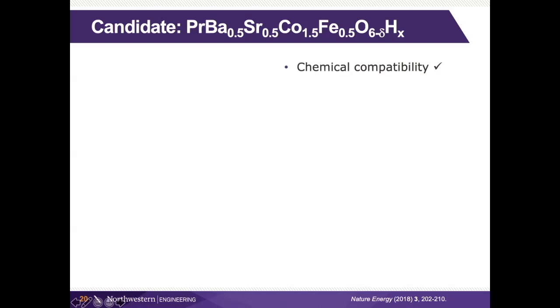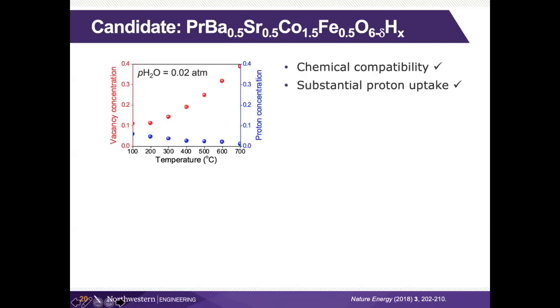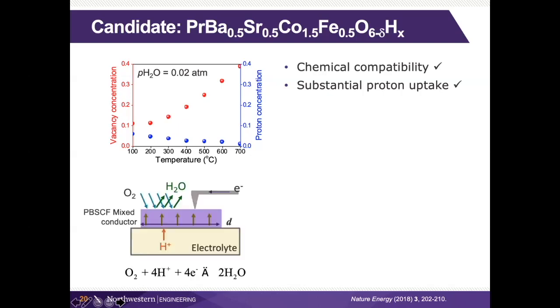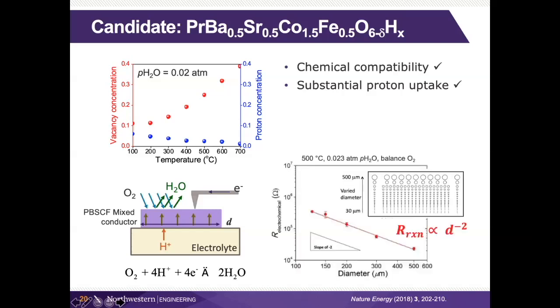We first established that it was chemically compatible with the other components. And then we established that indeed it will uptake a lot of protons when we expose it to some small amount of water partial pressure. So again, sort of squishy to oxygen ions, to protons, to water molecules, all of those can go through. And then we separately measure the electronic conductivity. So it's a good electronic conductor as well. And then we did an experiment where we varied the area over which this electrochemical catalysis can occur to establish that really are the protons going through and can we get a high activity. And so when we did that, we saw, yes, the activity scales with the diameter or with the area here. And because it scales with the area, that means the entire region is electrochemically active.